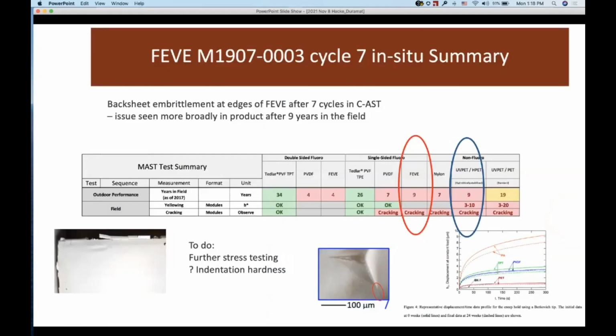We don't see any major cracking at this point in time, but we will do further stress testing to see if we can reproduce the kind of fractures that are seen in the back sheet after 9 years in the field. And we may also do indentation hardness, which produces cracks at the edges of the indentation. And also we can find changes in the displacement versus time curves as materials embrittle. So there's other tests we can consider doing as well.